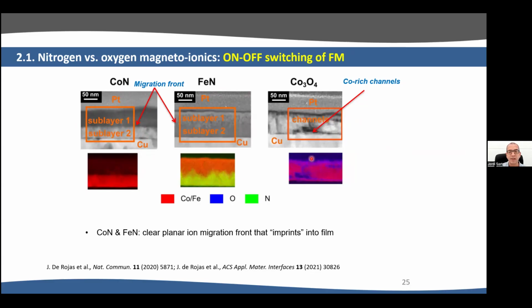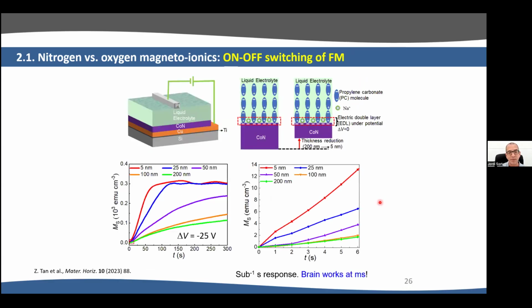And this is different than with cobalt oxide, where basically we had these perpendicular channels where oxygen was moving. So nitrogen seems to be released to the liquid in a layer-by-layer fashion, and it generates this planar front. And this is important for applications, as I will show you later. But going back to the speed, what we did next is to compare cobalt nitride films of different thicknesses.